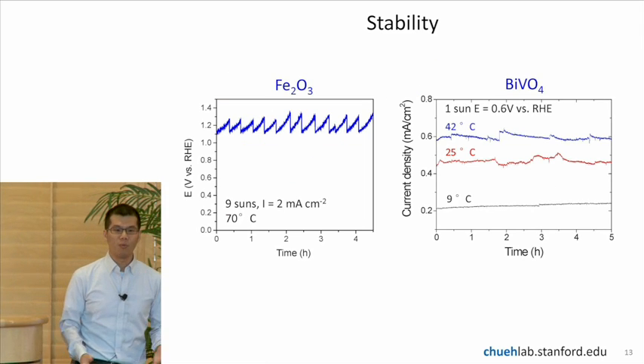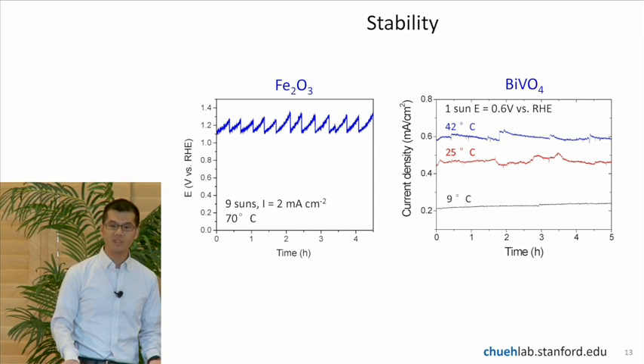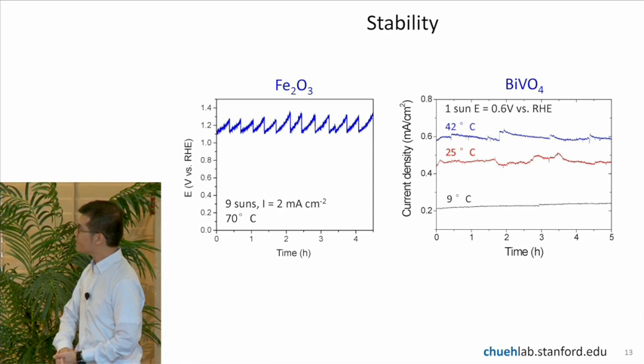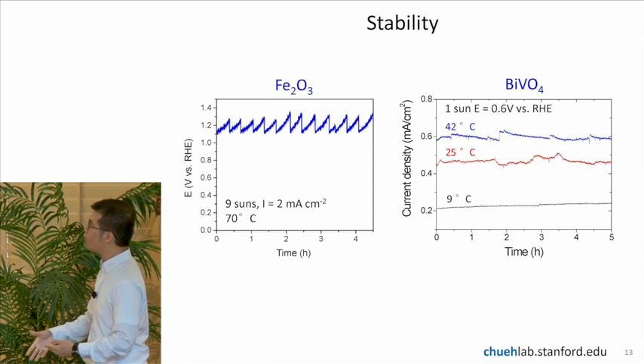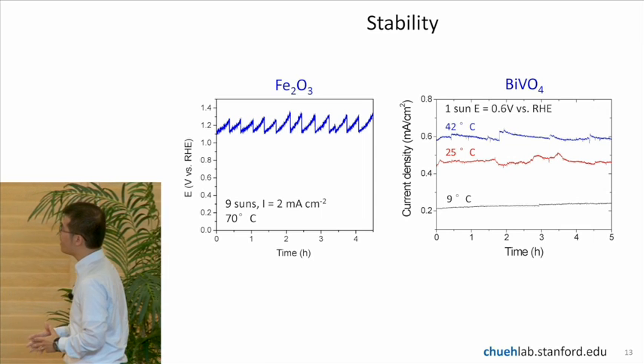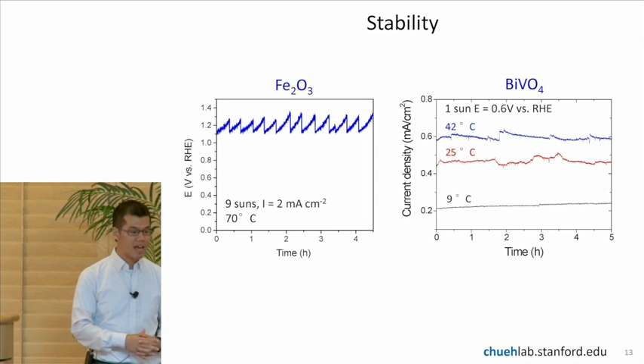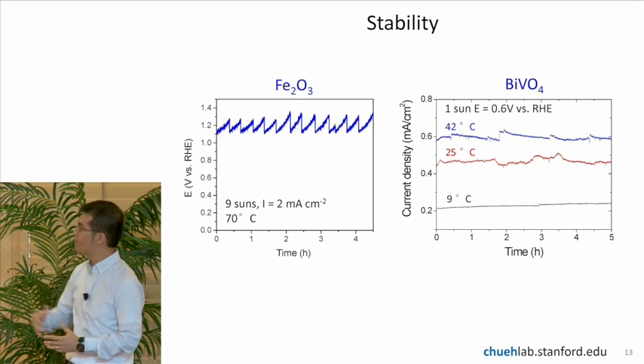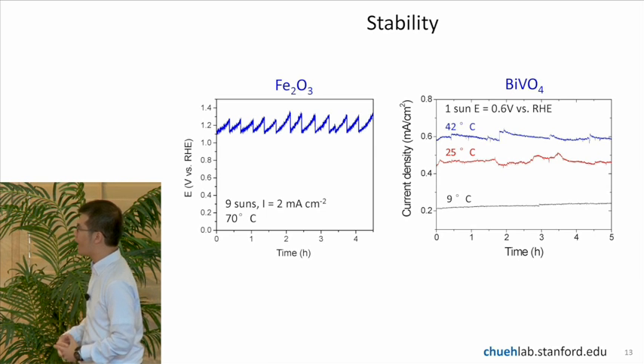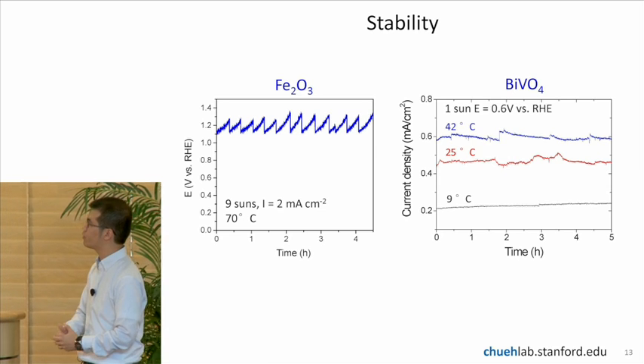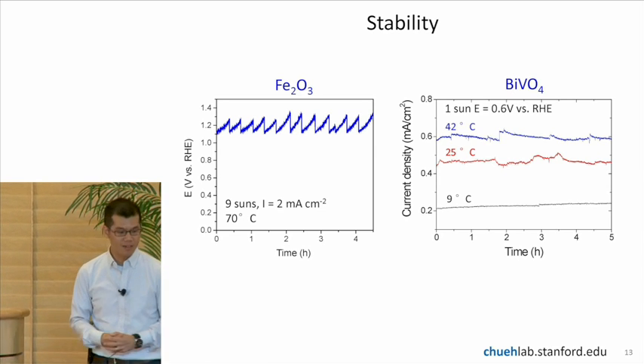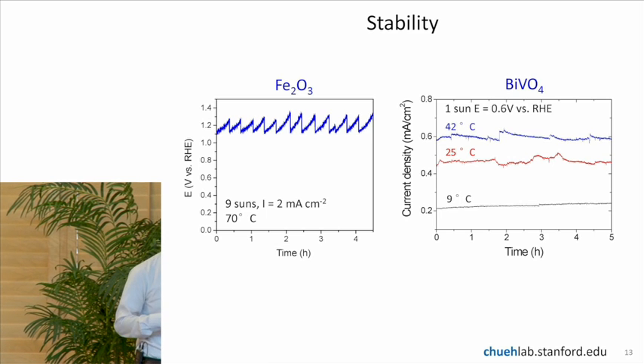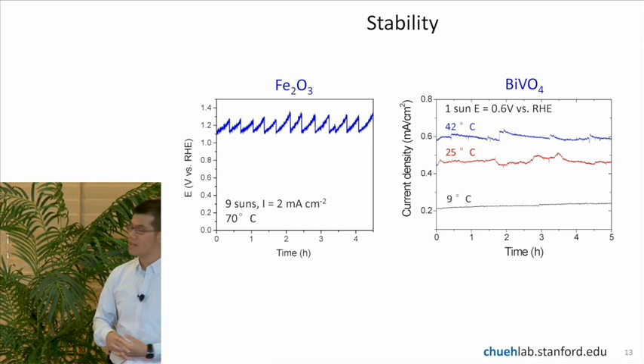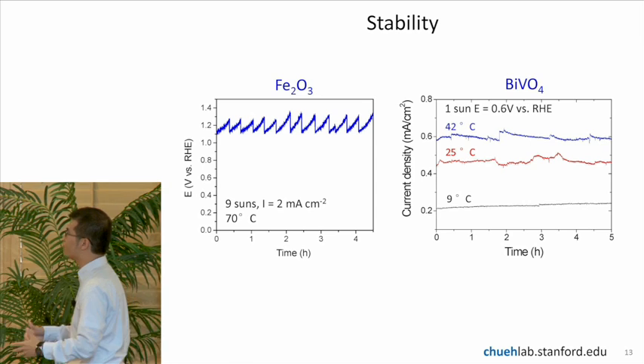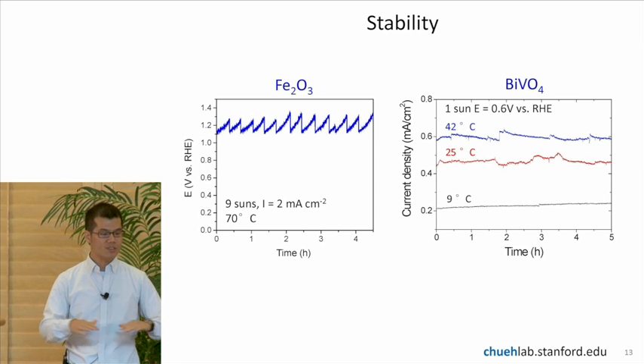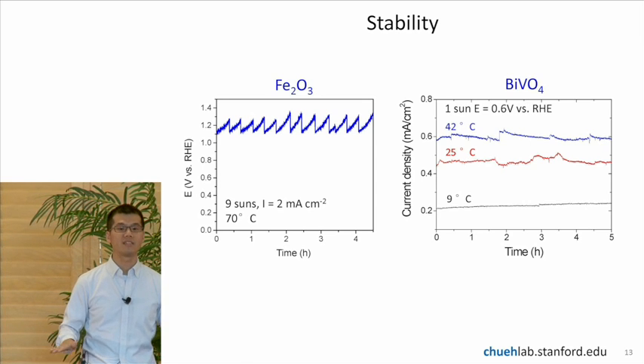So people always ask me, well, increasing the temperature generally decreases the stability. Well, it turns out that's not so much the case here. For both the iron oxide and the bismuth vanadate, the stability is actually rather good. So on the left plot, we have the iron oxide. This is where we held the current constant and we monitored the voltage. For the bismuth vanadate, we did the opposite. We held the voltage constant and monitored the current, just because 2 different people did the experiments. And we can see that the stability is excellent.